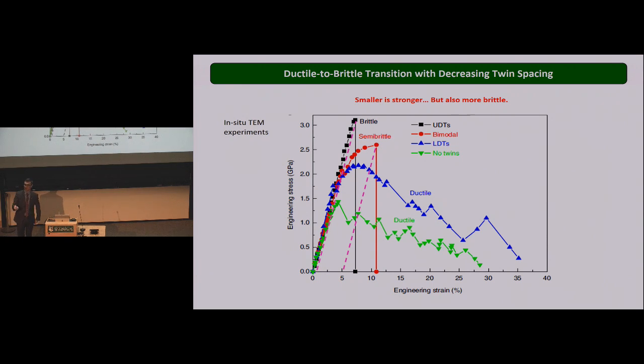You add some twins to it, you increase the strength, and the ductility is actually even better. That's the first video. Now those ultra high density twins, see, suddenly we achieve very, very high stress, but no ductility at all. So we go from a total ductile to brittle transition. And we even tested nanowires that contain segments of ultra high density twins and segments of low density twins, and the behavior is in between.